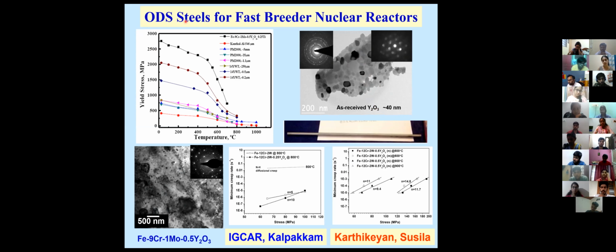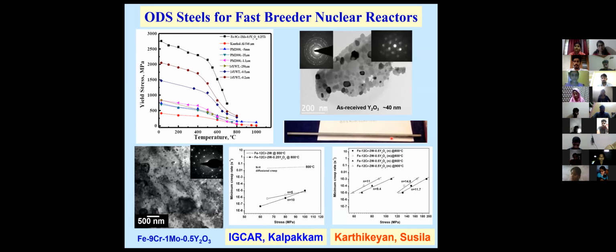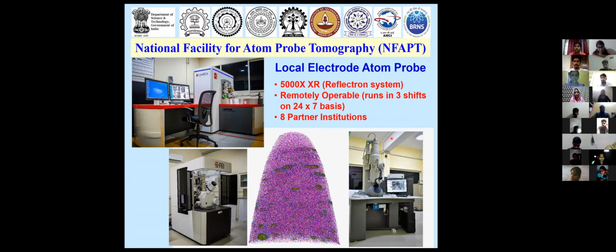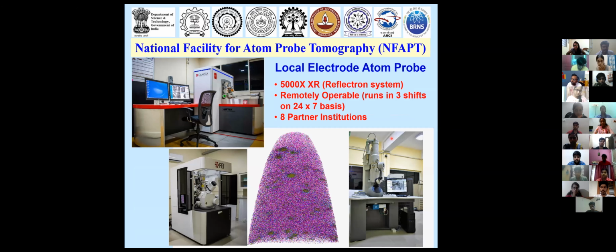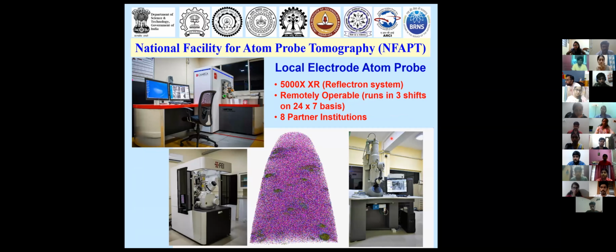And we have been able to make such tubes with the help of DMRL in Hyderabad and NFC in Hyderabad. This is a fascinating project, where we have been able to demonstrate that this material has very good creep properties, or high temperature strength resistance. Now, if I have such a material with nanoparticles embedded in it, can I see them? Can I find out the composition of this thing?